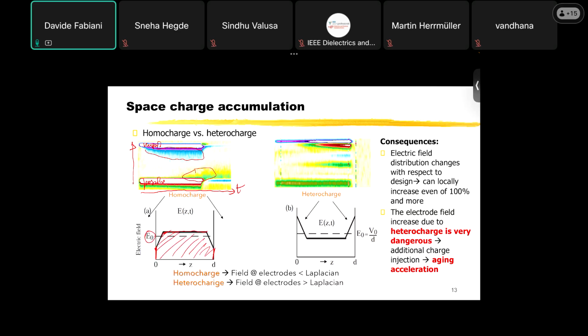While we can also have heterocharge accumulation. You can see here this positive charge accumulation close to the negative electrode. This is heterocharge accumulation. And heterocharge accumulation is very dangerous because it can provide an increase of the electric field close to the electrode with respect to the average field. And of course, if you have an increase here, you will get a decrease of the field in the middle of the material.